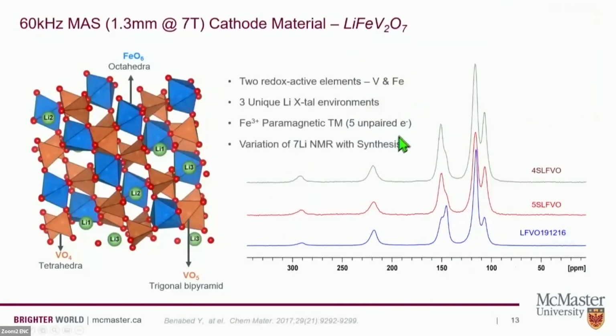And what she observed is this puzzling phenomenon that although our collaborators had given us a crystal structure of this material, said there should be 3 lithium sites, off you go, lo and behold, there are more than 3 lithium sites. And when we said, could you give us another material? We're not quite sure. They came back with different distributions of the population of essentially 2 sets of 3 lithium sites. And so this became a problem that Tiana and I really wanted to dig into.